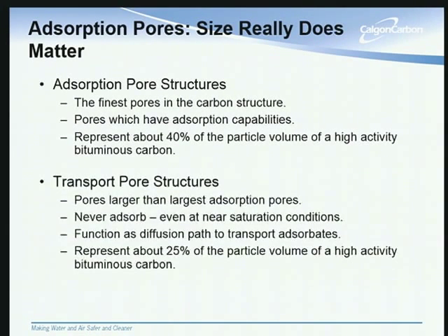Okay. When you consider the transport pores, again, these are larger. These never do any adsorption work, but again, they're necessary so that the adsorption pores can be reached. And these represent about 25% of the volume of a high-activity bituminous carbon particle.